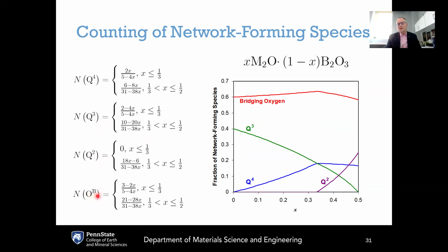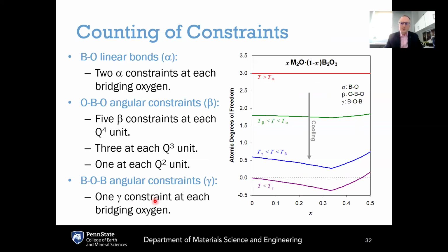This OB is the population of bridging oxygens. And so if you include the bridging oxygens here, and then the three different types of borons, this plot gives us the fraction of each type of network-forming species following the random pair model. And these equations then can be used as input into the temperature-dependent constraint model. The next step is to define the hierarchy of constraints in the system, starting at high temperatures.